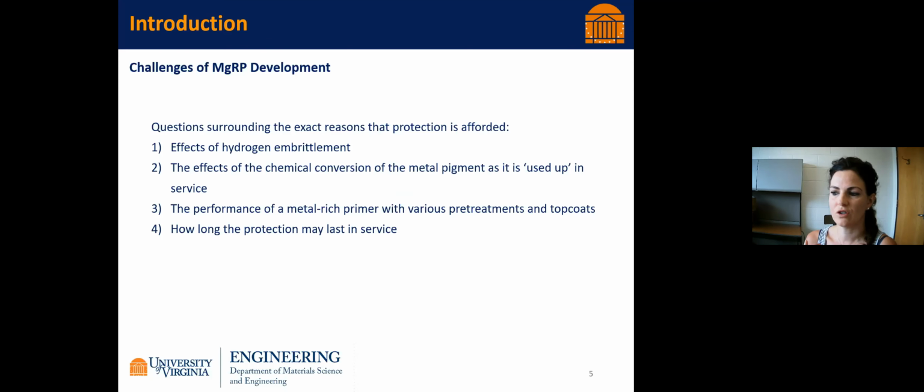are still questions surrounding the exact reasons that protection is afforded. And there are a few things that are uncertain in terms of the long-term protection. When we already have chromate, which obviously has its environmental issues, knowing that it's going to keep things protected is the number one priority. Some of the things that are of concern are the effects of hydrogen embrittlement. If we have a driving force that's too large in terms of the sacrificial anode relative to the substrate, we can then have the detrimental effect of hydrogen evolution, which can then embrittle the substrate.